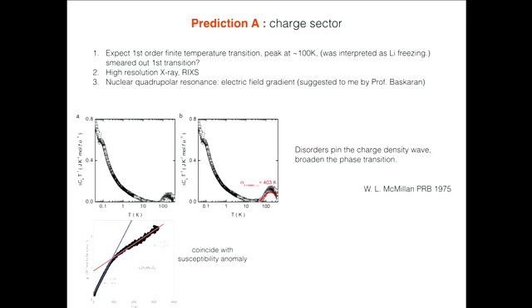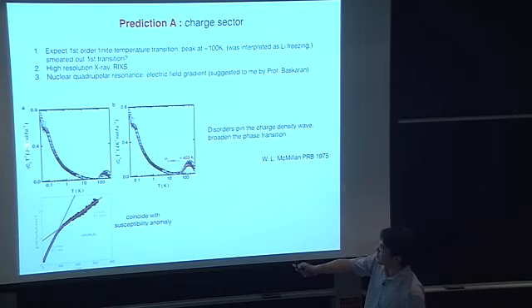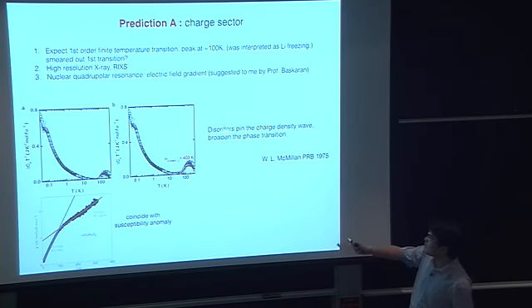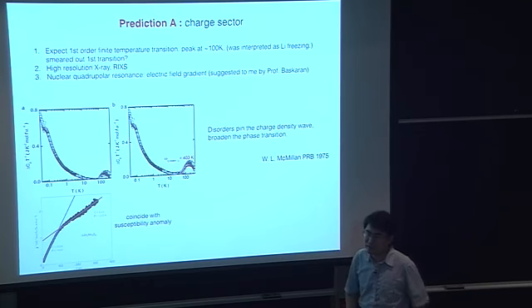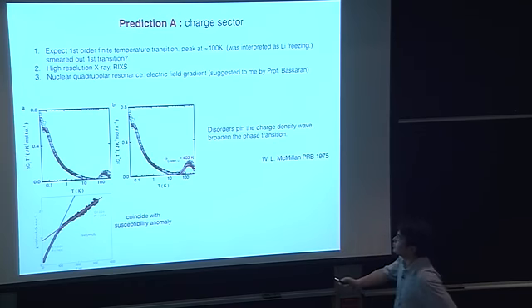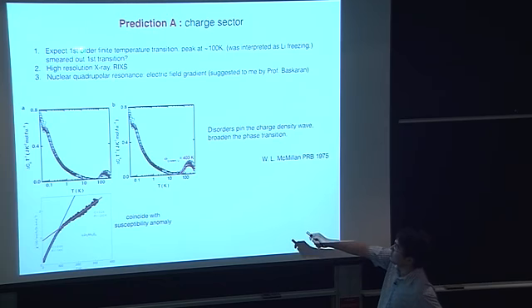And in fact, they measured heat capacity, magnetic heat capacity. There is a peak around 100 Kelvin, which is the turning point of this spin susceptibility. So this coincides with this peak. But this heat capacity peak is very broad. It's probably due to charge disorder because there are so many lithium here. Lithium is very mobile, and creates charge disorder. So the first transition, I expect it to be a first order finite temperature transition.